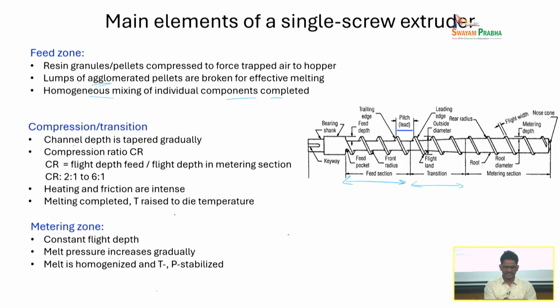So here what happens is, the channel depth tapered gradually. That means you can see from here to here there is a small increase in the diameter of the screw, and this will actually lead to something called a compression. And this compression is quantified by a factor called compression ratio. This is nothing but the flight depth at the feed location divided by the flight depth in the metering section.